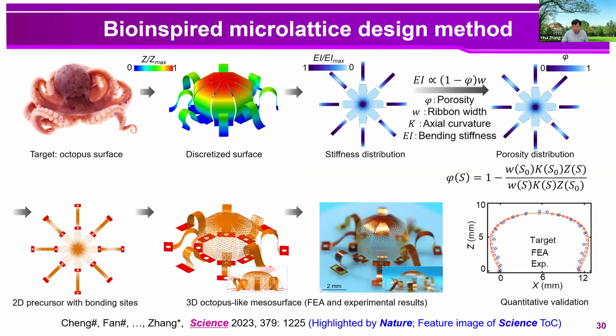So this model of the ribbon structure can be extended to the inverse design of curvy surfaces with centrally symmetry. So here, for a specific example of the octopus surface, the flow of inverse design is like this. We first use the idea of discretization to form this kind of design target with a set of developable ribbon components. And then, according to this solution, we can derive this kind of stiffness distribution and porosity distribution. With this information, we can construct the 2D precursor with micro-lattice design using fully triangular lattice patterns. And then we can testify the design by using numerical experiments and real experiments.